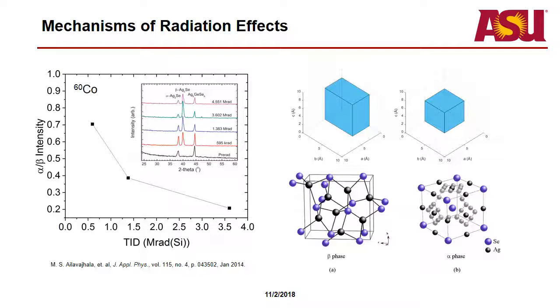So this germanium selenide electrolyte is actually a mixture, it's a glass. And so you'll have these nano phases of silver selenide, and then around those nano crystals you'll have a backbone of germanium bonds, or germanium selenide bonds even. But essentially that backbone puts a lot of pressure on the silver selenide, and so it allows it to exist in this higher temperature state.